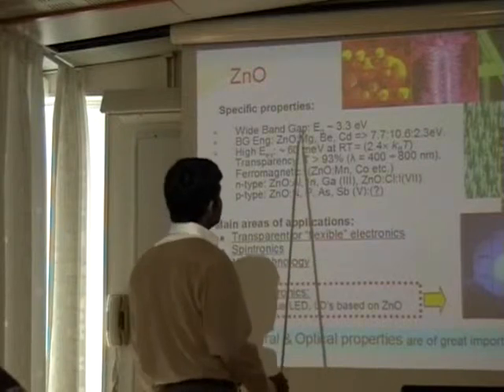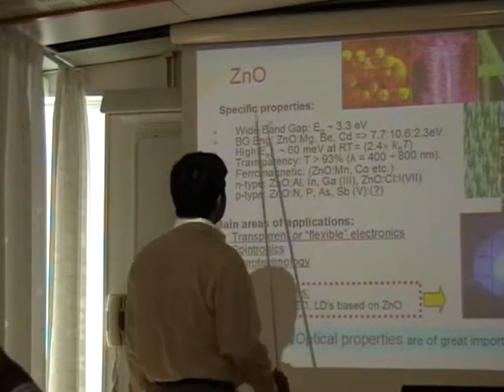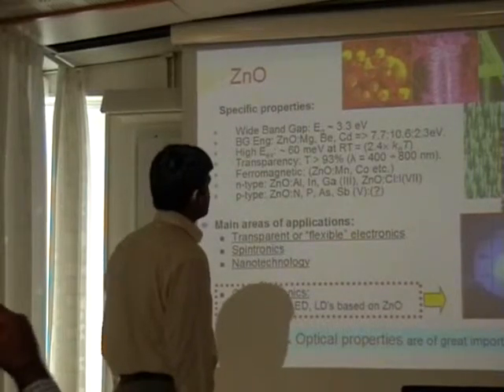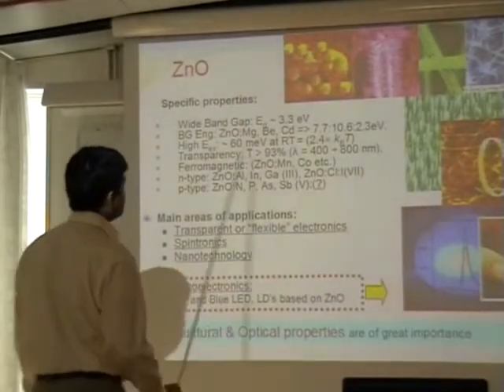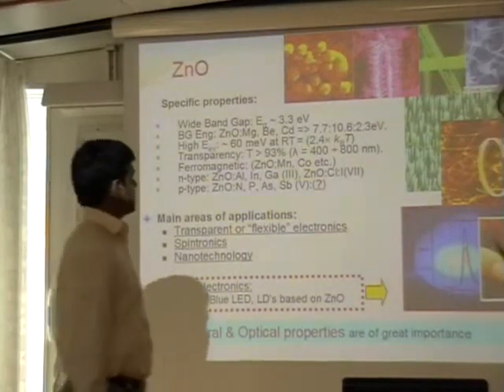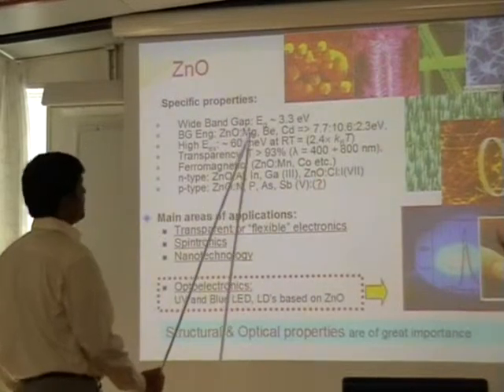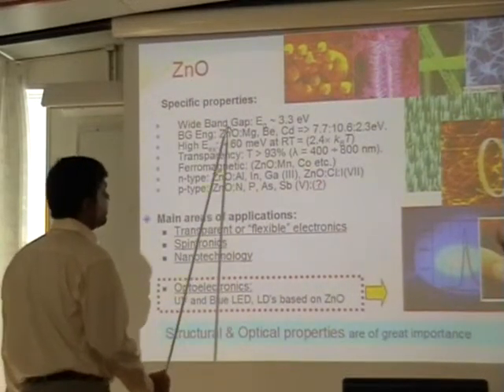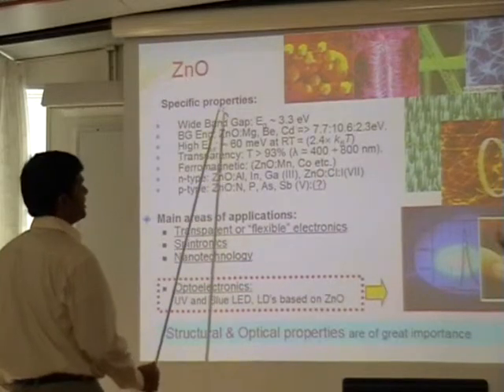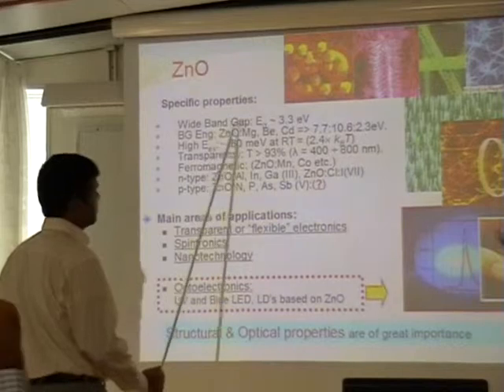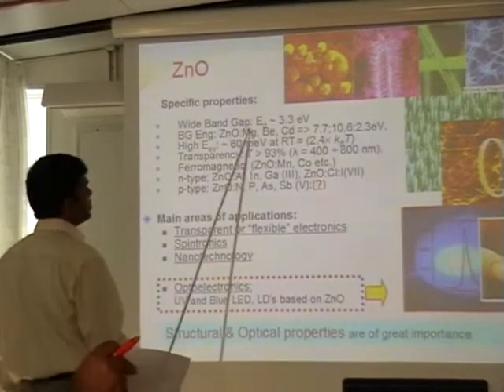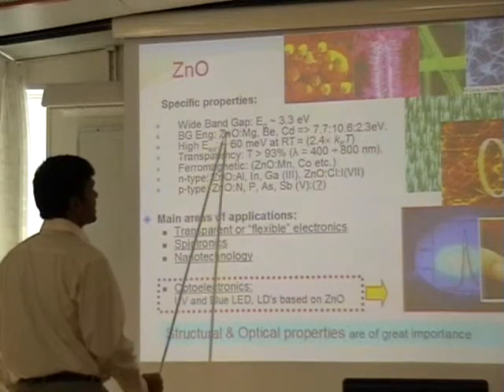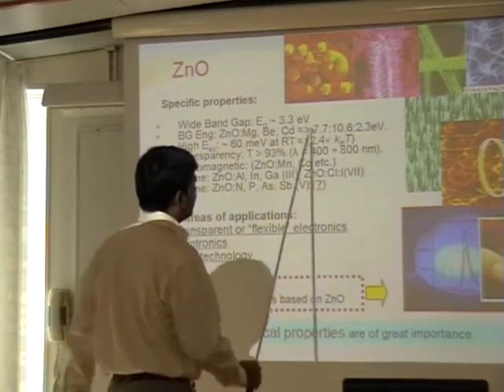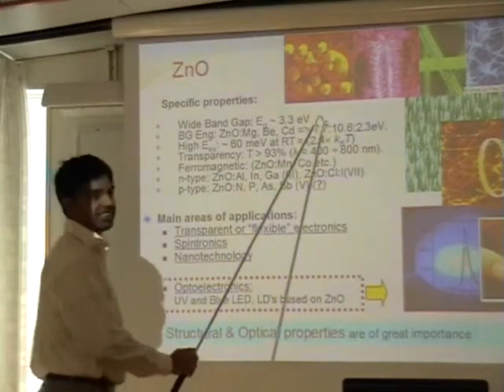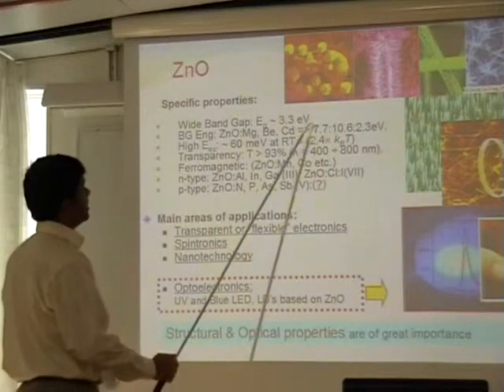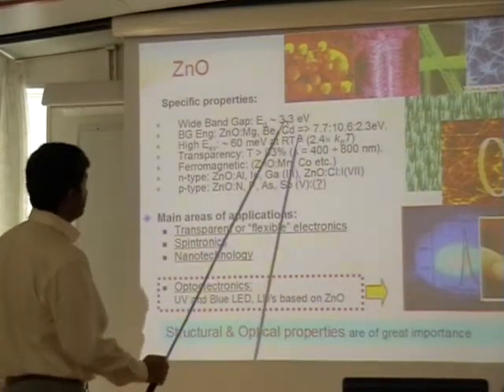With the modulation of magnesium in zinc oxide, they are used in optoelectronic applications. Actually, zinc oxide has a wurtzite structure, while magnesium oxide is cubic, but with the doping or composition of 40%, zinc oxide remains wurtzite, but when the composition increases up to 60%, the zinc oxide changes from wurtzite into cubic, and the band gap increases dramatically. And that's why they are used in ultraviolet lasing.